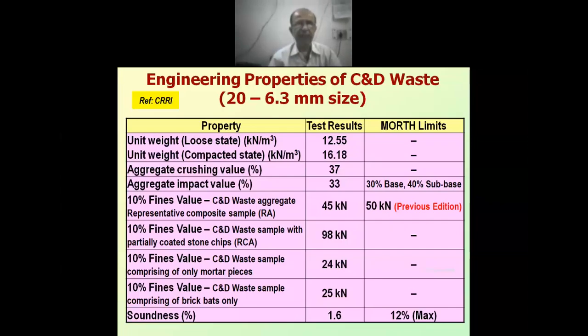Then the engineering properties of the C&D waste aggregate, 20 to 6.3 mm size: unit weight in loose state and unit weight in compacted state, 12.55 and 16.18 kilonewton per meter cube. There are no MORTH limits for that. Aggregate crushing value is around 37%, which is done by the crushing value strength test, and there is no MORTH specification for crushing value as such. Aggregate impact value of this 20 to 6.3 mm size is 33%.